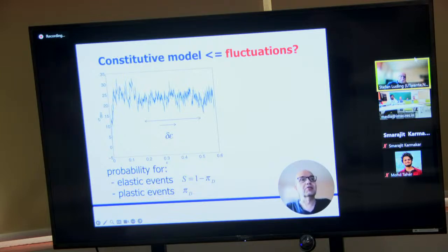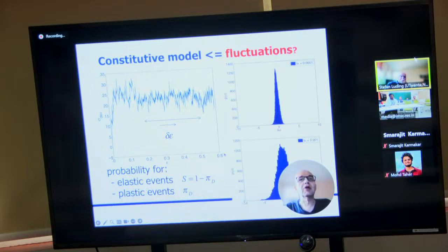But in this stress strain picture, we can analyze all the fluctuations. How do we do this? We take the probability for stress going up, and the probability for stress going down, that's on the horizontal axis here. Delta sigma being positive or negative means your stress is increasing or decreasing. And delta epsilon is the range which we look forward. If we use a small range, we get a narrow Gaussian distribution, it's almost random.